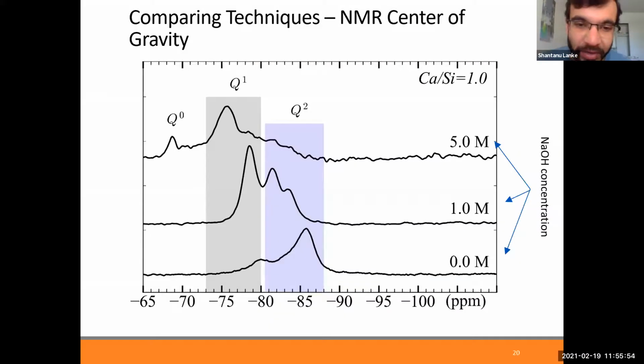So my question is, what kind of functionality do the silicon centers have? Because when I recorded NMR spectra for silica, I used to get Q4, Q3, and Q2 at chemical shifts of around -110 for Q4, somewhere around -100 for Q3,